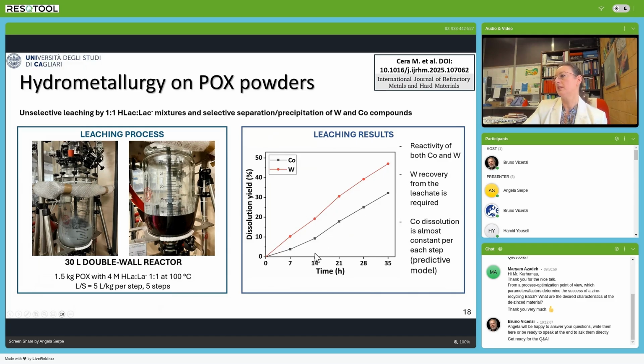So through this process, we were able to dissolve both metals. If we just wanted to change the amount of cobalt in the solution, in particular decrease it, this would not be necessary, because tungsten can in principle remain in the solid residue. But it is really interesting when we have other metals in the mixture, because in that case we are able to dissolve both cobalt and tungsten and obtain the selective recovery at the end of both of these metals, avoiding contaminants or metals that are not desired in the mixture.